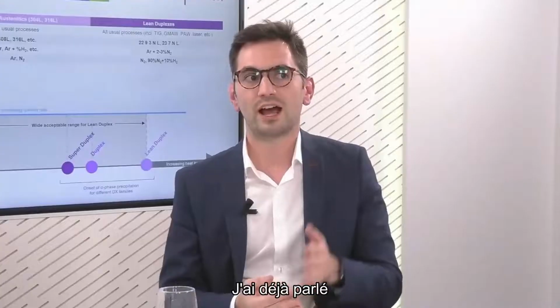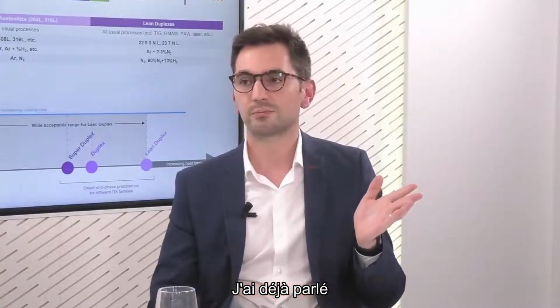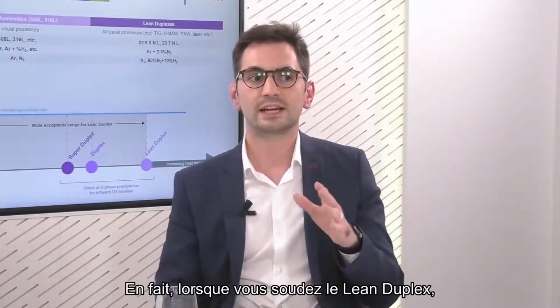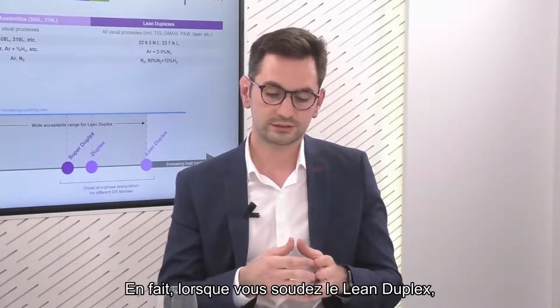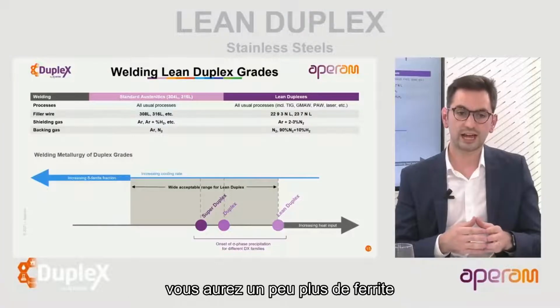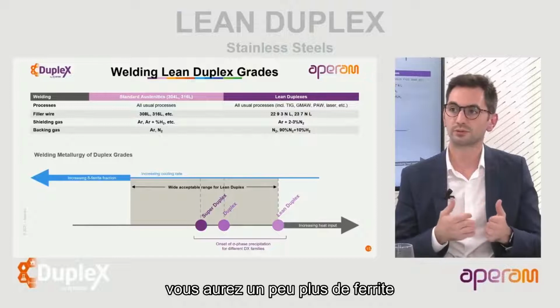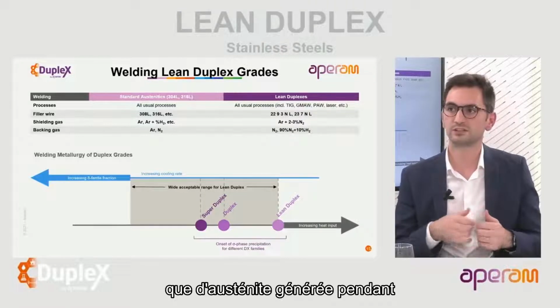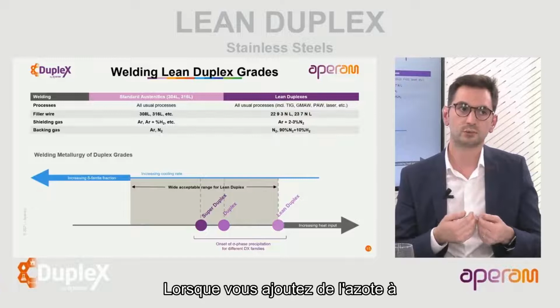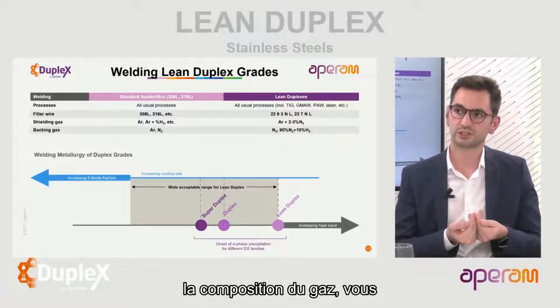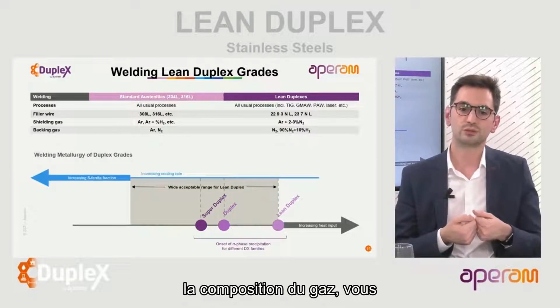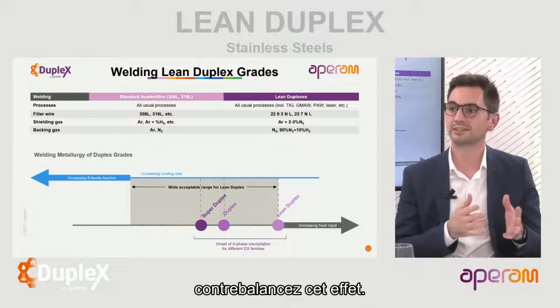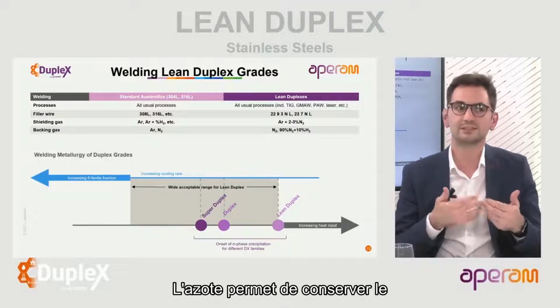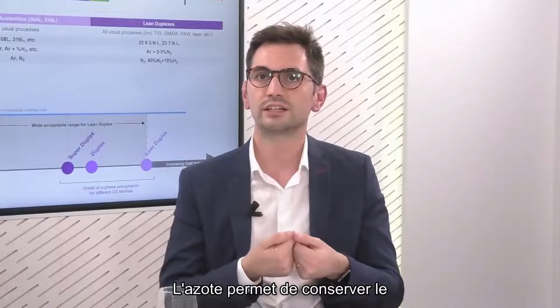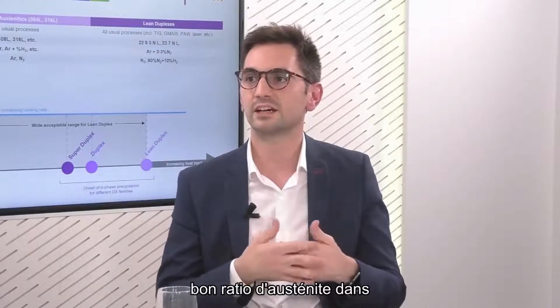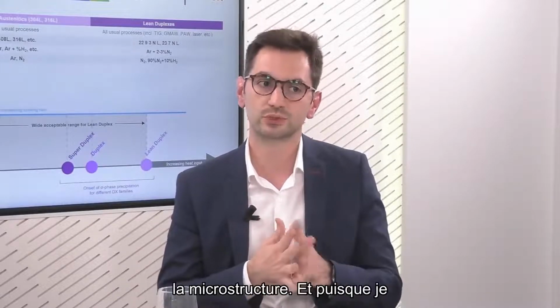So I was talking before about the microstructure of the duplex. Actually, when you weld the Lean Duplex, you will have a little bit more of ferrite than austenite being generated during the welding. And so when you add the nitrogen to the composition of the gas, you counterbalance that effect, and so the nitrogen allows to keep the right austenite ratio in the microstructure.